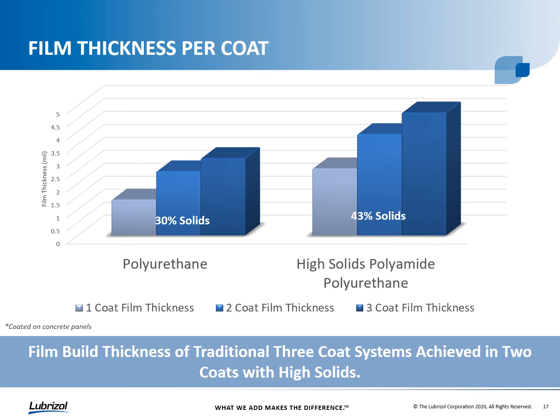And in this example here, we're comparing a traditional polyurethane clear system formulated at 30% solids to the high solids polyamide-based polyurethane formulated at 43% solids. And what we can see is that we're effectively putting down more material in each coat. After a 1, 2, and 3 coat application, you can see with each subsequent coat, we're putting down more and more film thickness, so that after just 2 coats of the high solids material, we've in essence put down a greater film thickness than 3 coats of the traditional system, ultimately allowing you to reduce a coat.